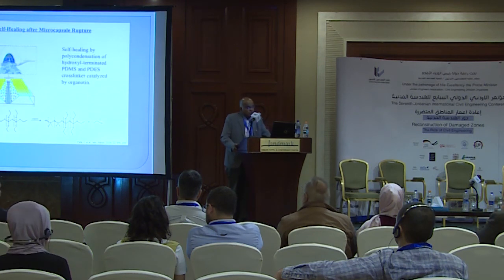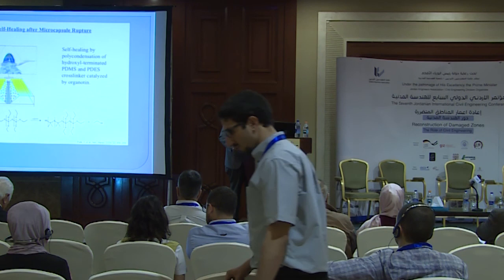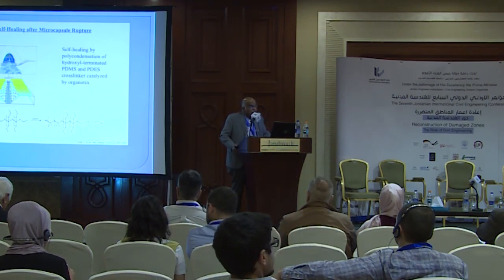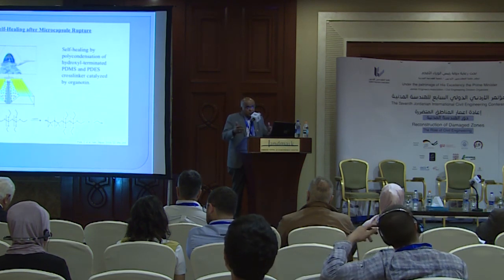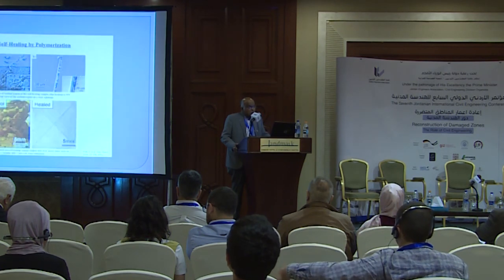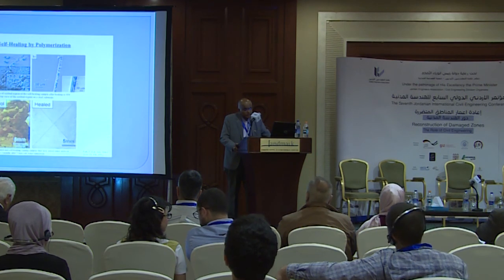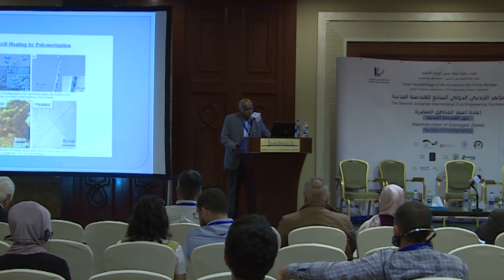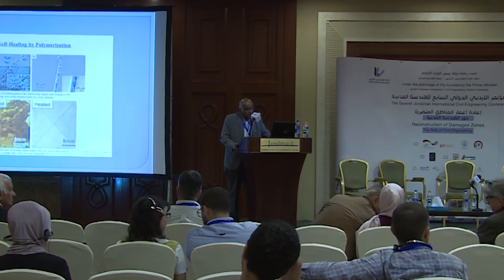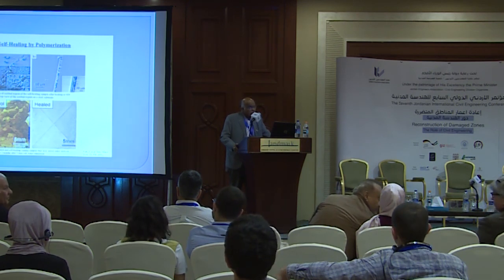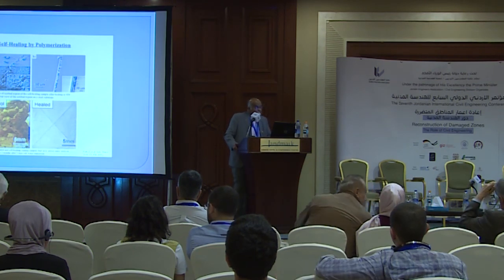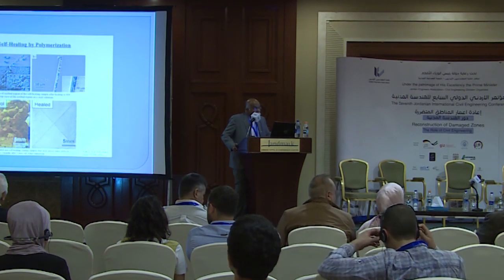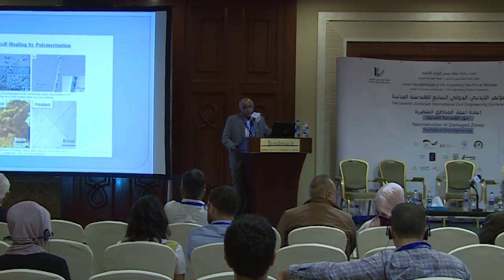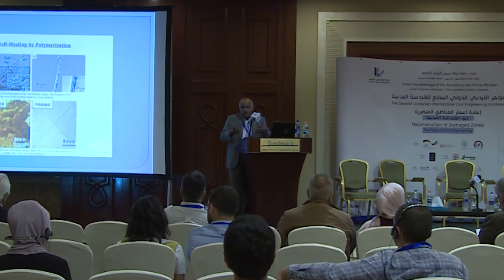So how this healing occurs after rupture, this is one of the ways, by means of reaction and forming cross-linked material. So the crack, wherever it is, this liquid will come out and form a polymerized cross-linked compound. So this is another mechanism. This after your thermal and the other electro mechanisms, we have the polymerization, which is used for self-healing. Some of the micrographs are there showing how this is basically glue which is hardening. It's some kind of super glue or whatever you can call. So this cross-linking is how this super glue hardens.